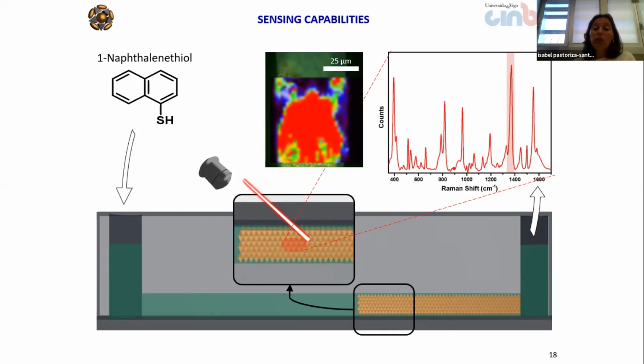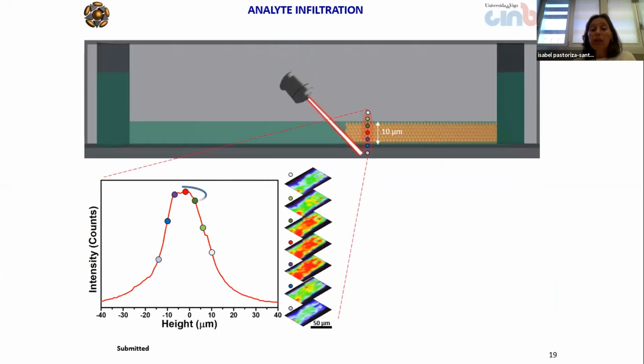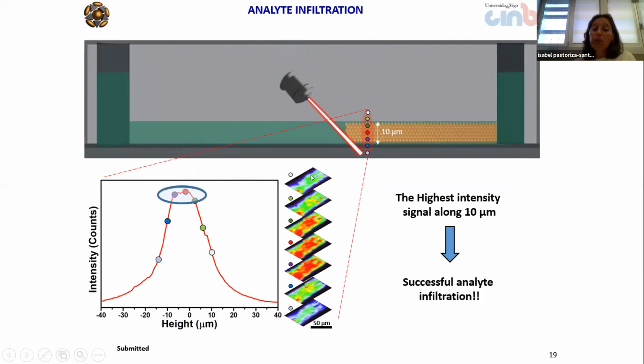So in order to check the infiltration, what we did was an in-depth analysis of the SERS response of the supercrystals. And this is the result. These are SERS mappings recorded at a certain vibrational mode of the molecule, and each map corresponds to a different height. And this is the average intensity of the SERS mapping versus the height. And you can see here that there is a plateau of maximum intensity. The highest intensity signal occurs along 10 microns, and this 10 microns corresponds with the height of the supercrystals, meaning that the molecule is homogeneously distributed in the whole supercrystal.